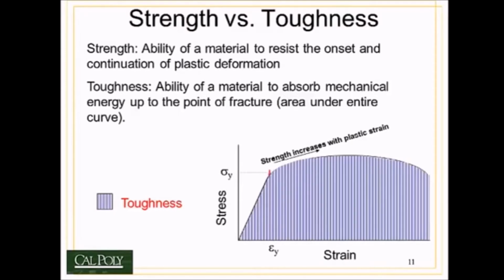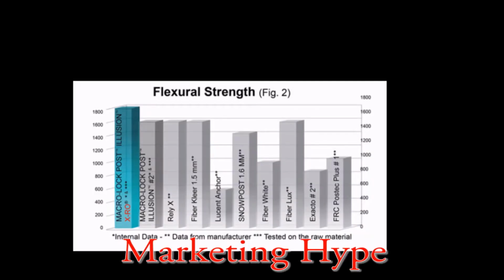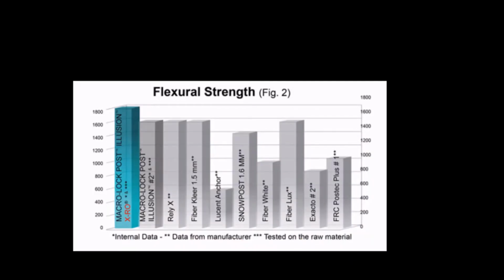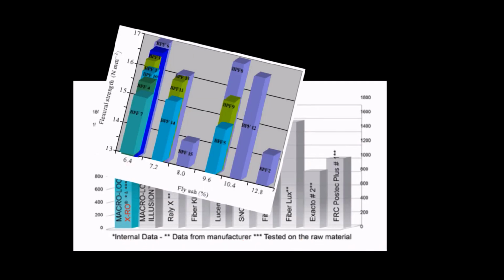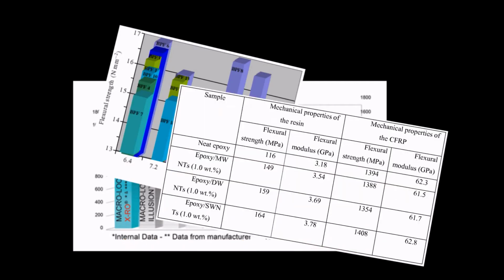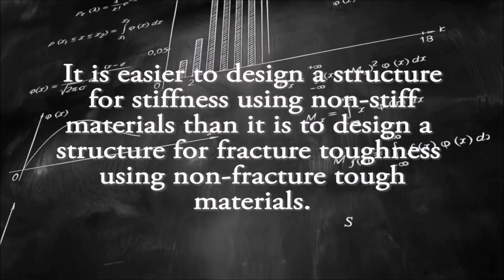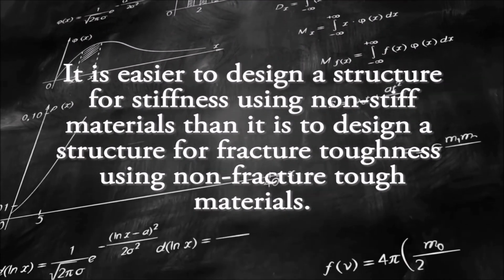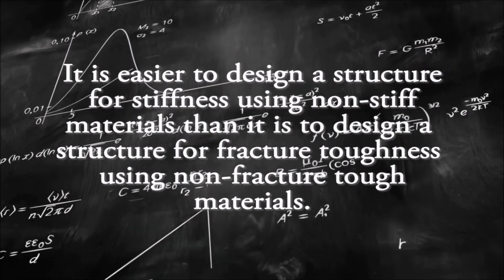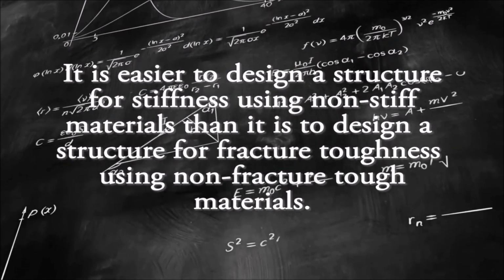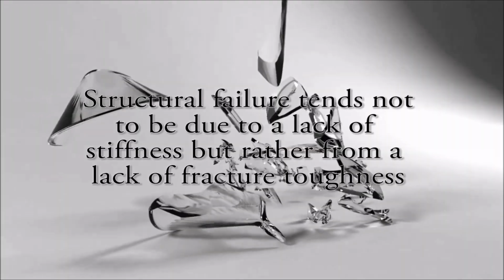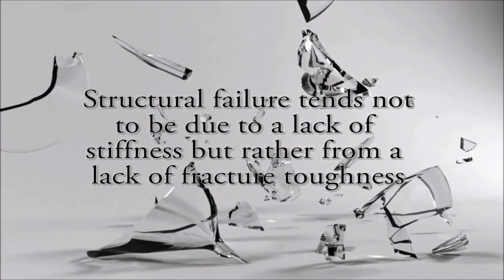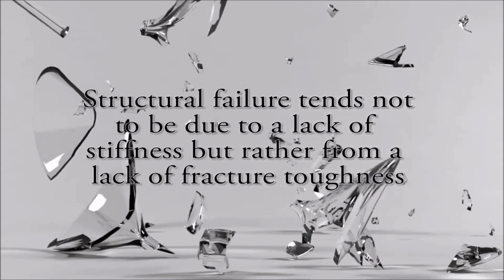Fracture toughness is the quality of a material to resist the rapid propagation of cracks. Marketers of glass fiber reinforcements sometimes try to use flexural strength and flexural modulus, which are measurements of stiffness, to try to suggest clinical performance. However, any structural engineer will tell you that it is easier to design a structure for stiffness using non-stiff materials than it is to design a structure for fracture toughness using non-fracture tough materials. In other words, structural mode of failure tends to not be due to a lack of stiffness, but rather is due to a lack of fracture toughness.